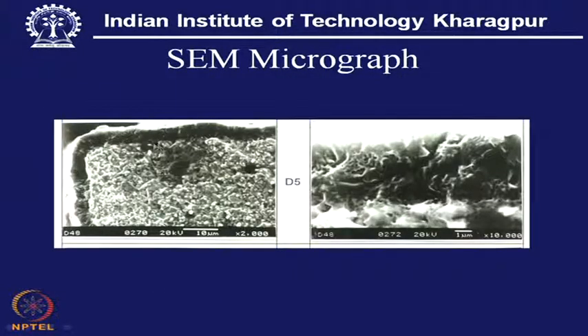So, it covers, and apparently there is no fault in the interface, but still with higher magnification we can look into that, what is the fault, how this interface is built, that can also be possible. Then comes uniformity in the thickness of the coating. Here we find the thickness is a little more compared to the thickness on this side. So, that is also one thing one has to look into. And what additionally we can see is the substrate itself, the substrate is a hard metal in this case, of course.